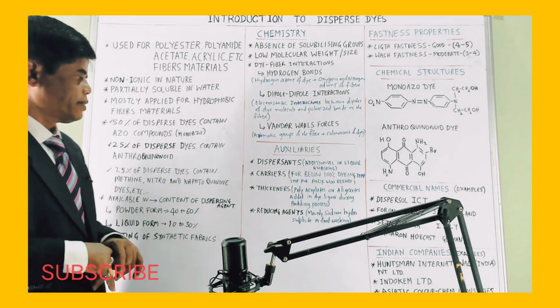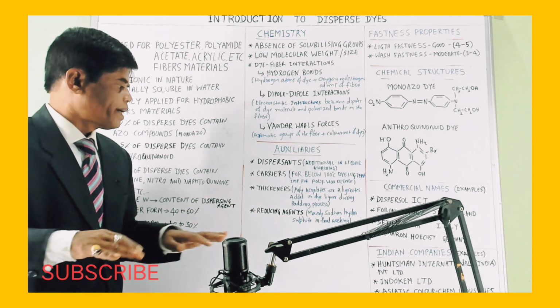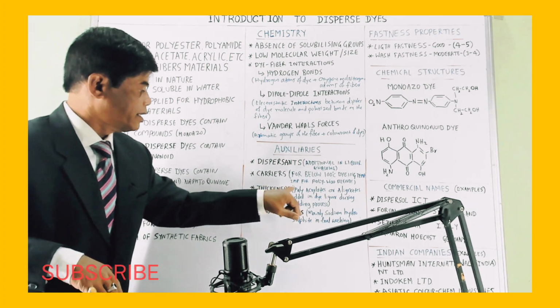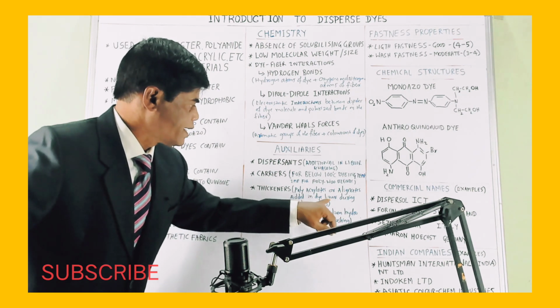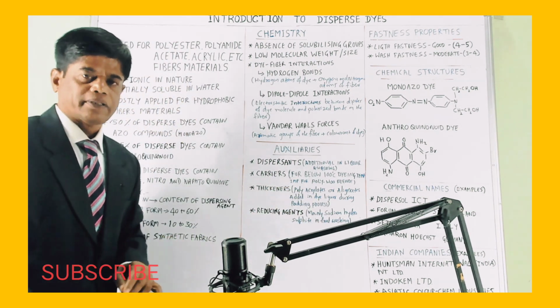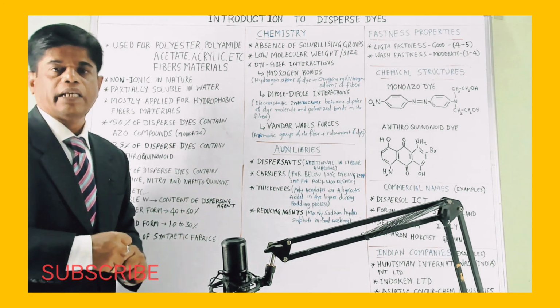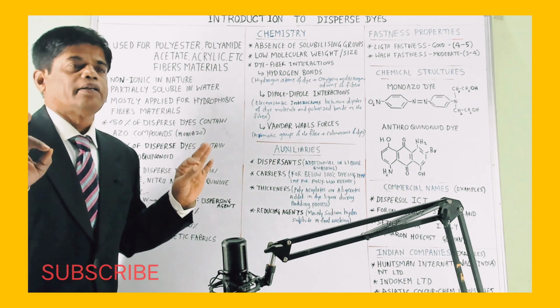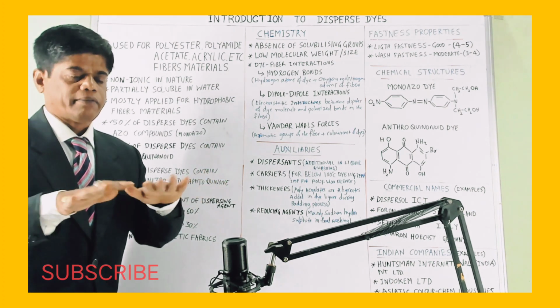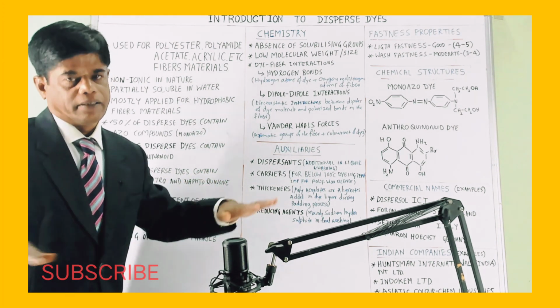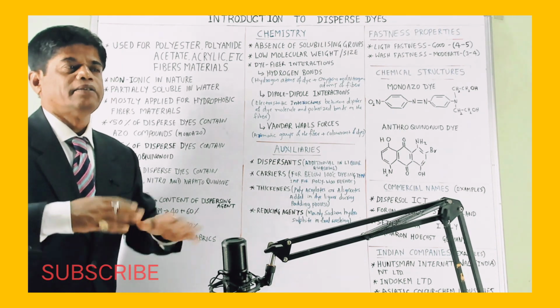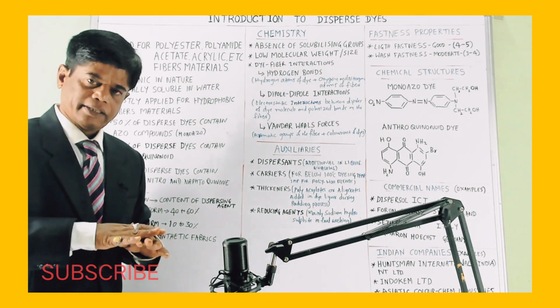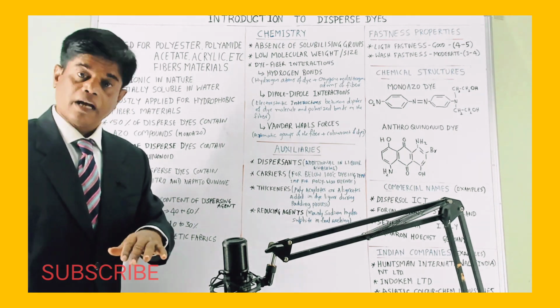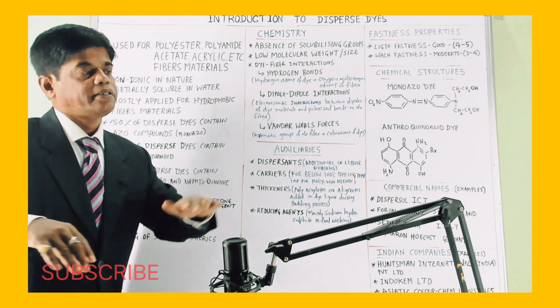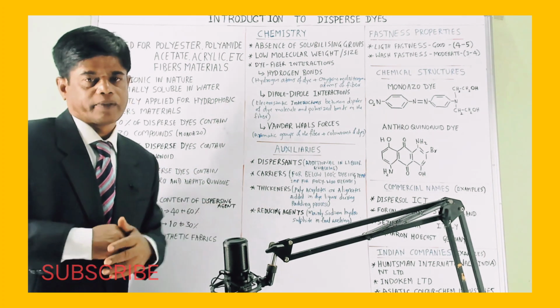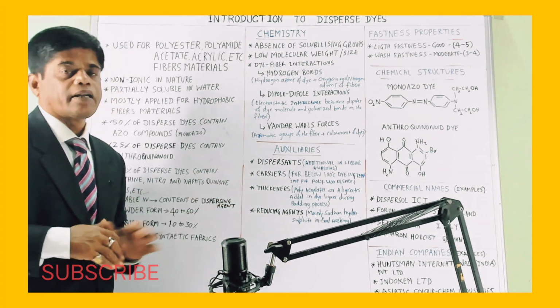So to avoid unevenness during padding, thickeners are added, that is polyacrylate and or alginate, added in the dye liquor during the padding process. In the padding process, to hold dye molecules to each other evenly and spread evenly, gum-like thickeners are added that will take care of leveling of the dye. Otherwise, if the dye is thin, some part of the fabric takes a dark shade and some part takes a light shade. To maintain even shade, thickeners are required.